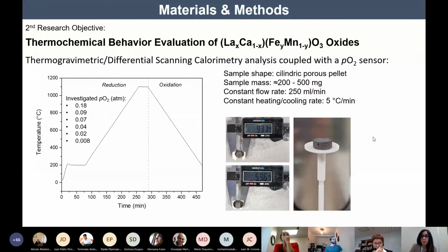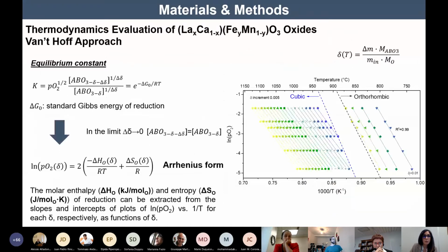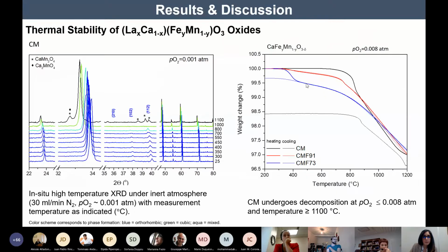proper conditions for the materials to be in equilibrium conditions during the cycles, in order to use the Van 't Hoff approach for the evaluation of the thermodynamics. So we extracted the enthalpy and the entropy of the materials, which were unknown, from the Arrhenius plot that we obtained from the δ profiles that we got from TGA analysis.